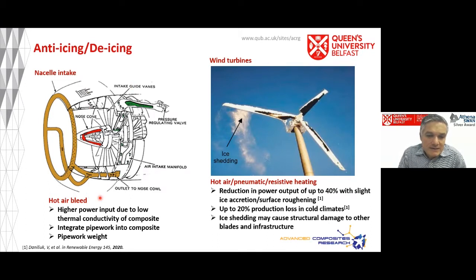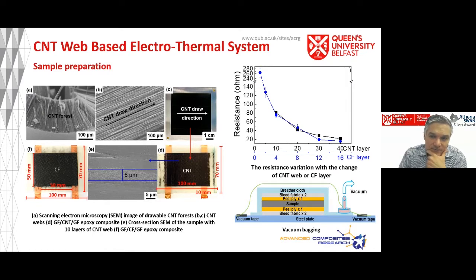So if I now look at the web itself, the initial investigation was to compare a CNT web with the direct heating of carbon fiber UD plies. And if you look at resistance versus the thickness of either the carbon nanotube layer, because obviously what you saw was a single layer being drawn out, but of course you can stack these up. And if we stack them up at say 10, 20, 30 layers, then you can look at how your resistance changes. And as you would expect, we're not talking about resistivity here, we're talking about resistance, right? So as you would expect, your resistance drops as you increase your thickness.